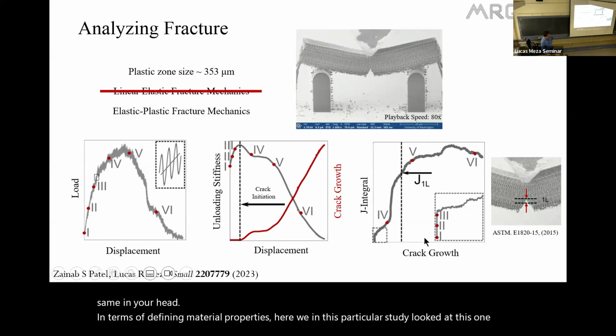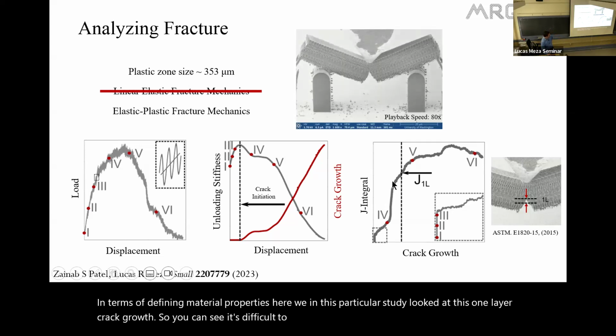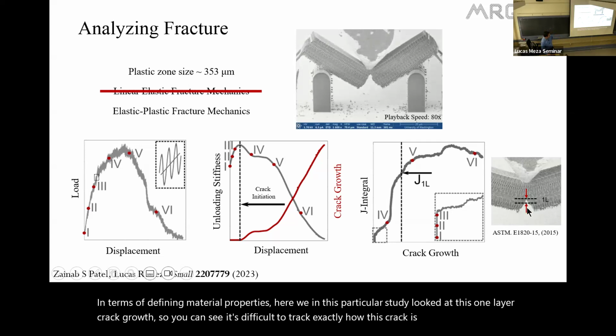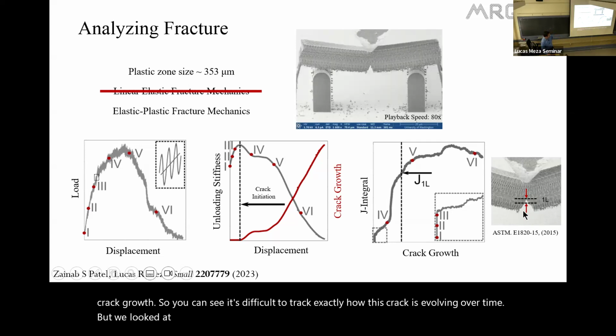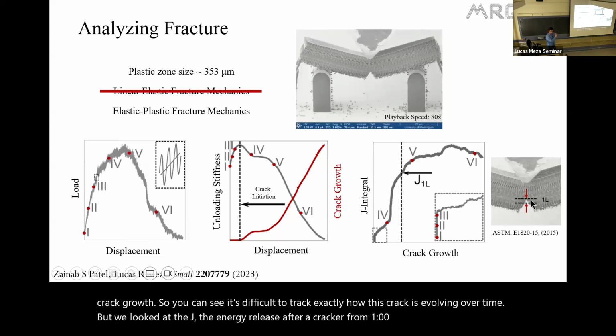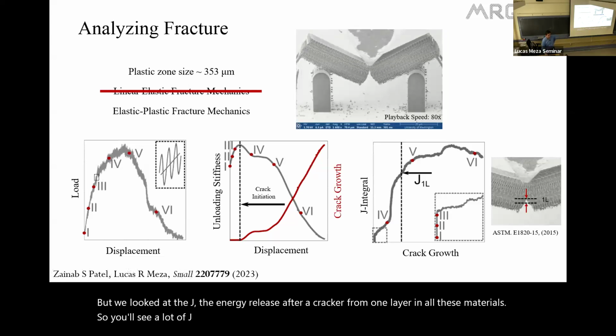In terms of defining material properties here, we, in this particular study, looked at this one layer crack growth. So you can see it's difficult to track exactly how this crack is evolving over time, but we looked at the J, the energy released after a crack had grown one layer in all these materials. So you'll see a lot of J1Ls being reported here.